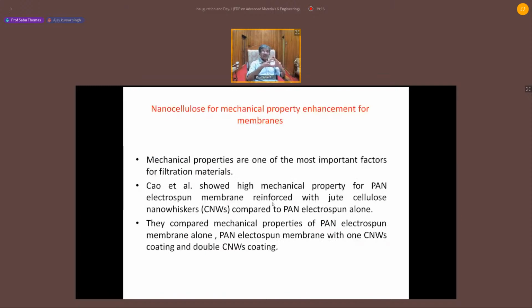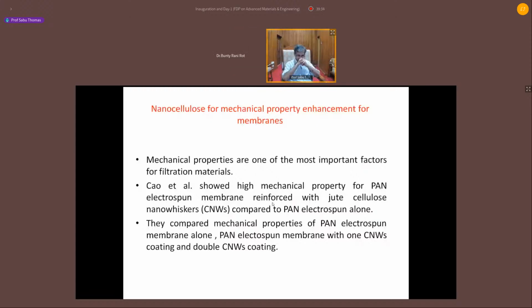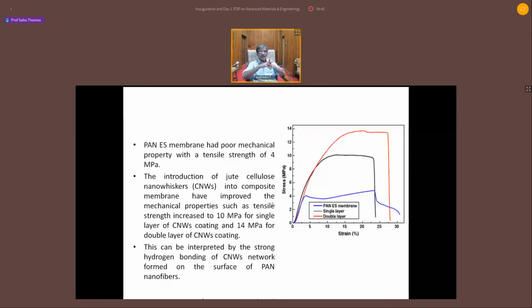Nanocellulose is again a fascinating material to reinforce typical commercial filters. Commercial filters made by electrospinning, for example, polyacrylonitrile filters made by electrospinning, are mechanically weak. So, if you look at the work of Cao et al., he suggested that if you reinforce these commercial filters with nanocellulose. Look at this. This is a single layer coating, this is a double layer coating. The mechanical properties are substantially improved. If you give a coating on one surface, the mechanical property went up to 10 megapascal. Double layer, it went up to 13.5 megapascals. So commercial membranes could be strengthened by coating nanocellulose.